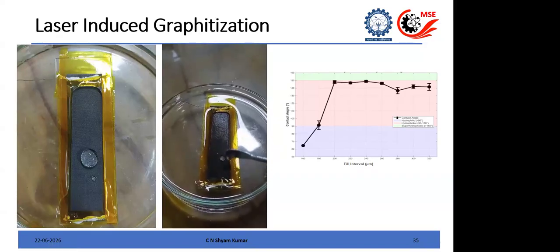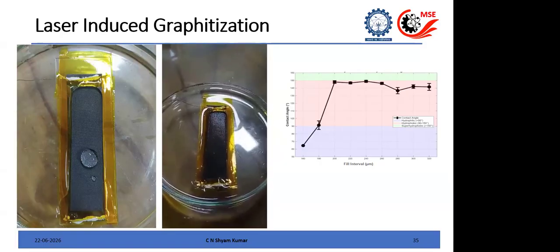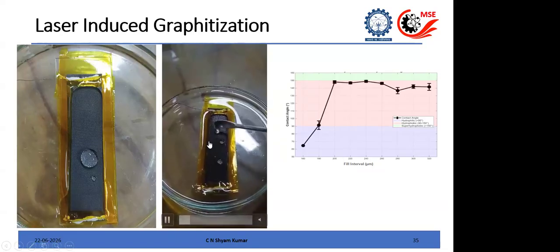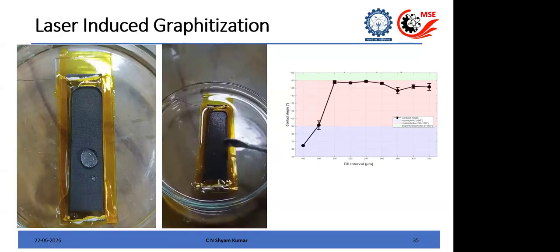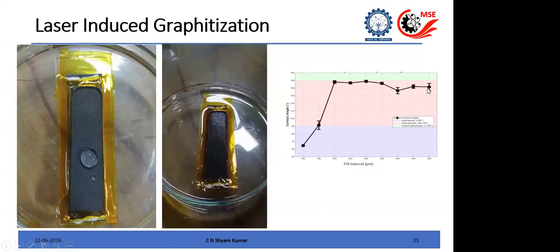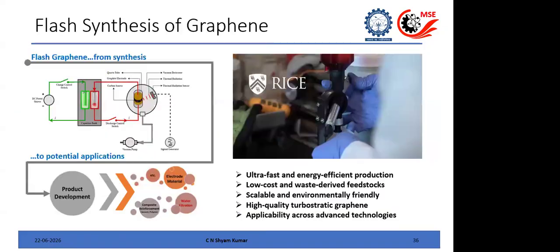And these carbons can be used not only for heaters, but you can actually change the surface properties by changing the laser parameters. So you can see this is a super hydrophobic surface which is formed by laser graphitization, and then you can tune the contact angle by changing the laser parameters. Some examples, it is not limited to just graphitization, but you can also use it to optimize different properties.